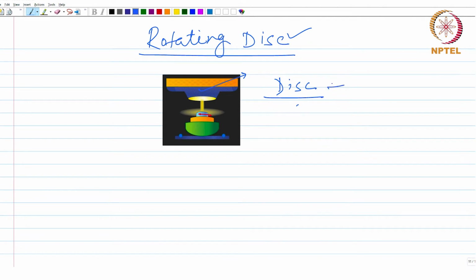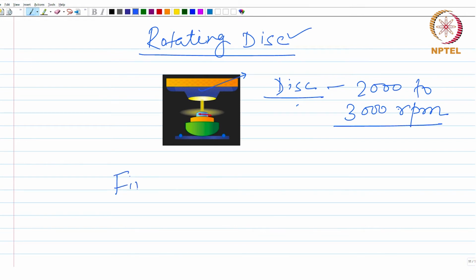Okay. So, the disc will be rotated at very high RPM, between 2000 to 3000 RPM, in that range. And as the molten metal falls onto this rotating disc, it is subjected to a centrifugal force, and the metal breaks down into droplets. Okay. And as far as the powder particles are concerned, in this case the particles are finer compared to the previous method, that means the rotating rod method.